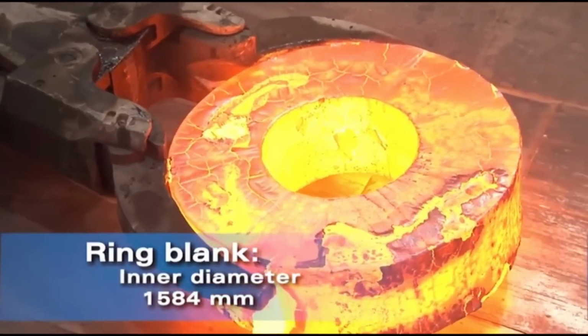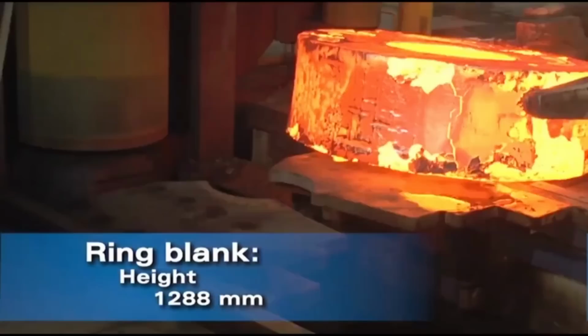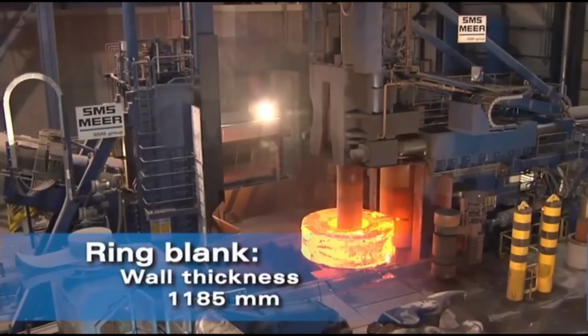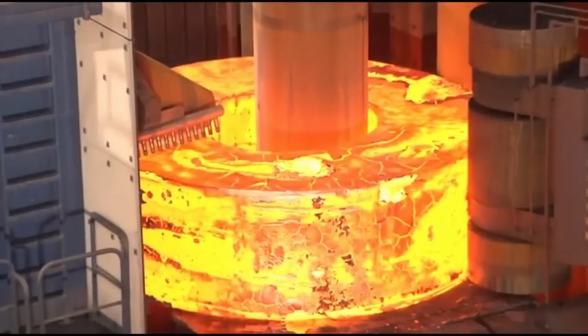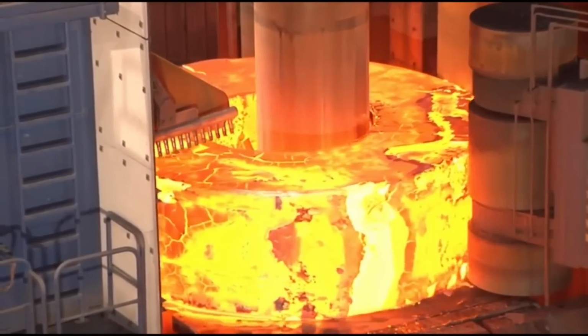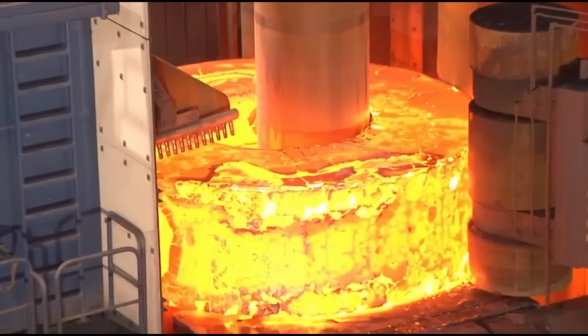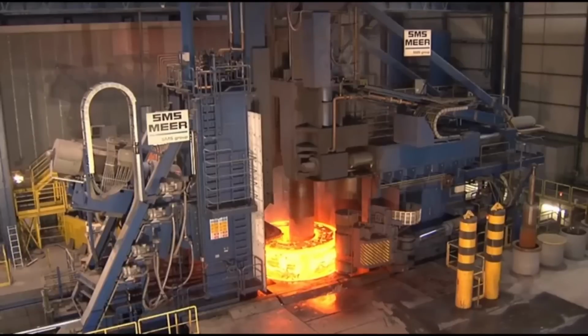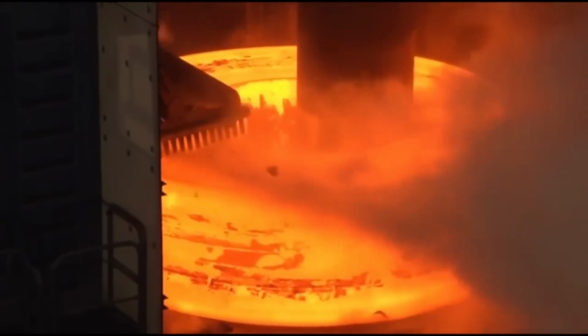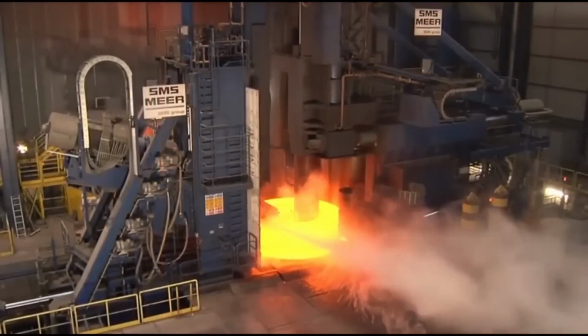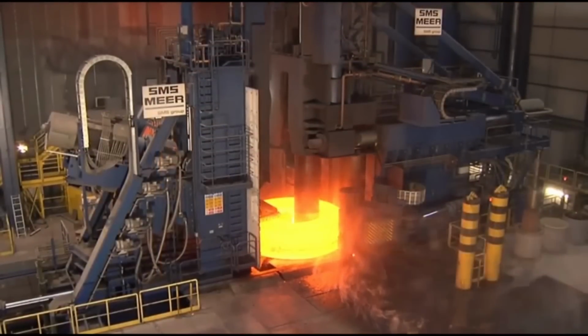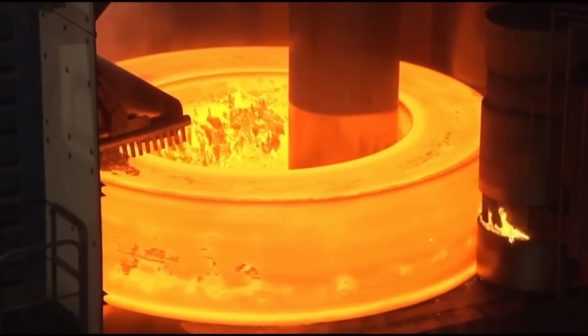Outer diameter, 3,954 millimeters. Inner diameter, 1,584 millimeters. Height, 1,288 millimeters. Wall thickness, 1,185 millimeters. A much larger ring blank with an outer diameter of 3,954 millimeters, an inner diameter of 1,584 millimeters, a height of 1,288 millimeters, and a substantial wall thickness of 1,185 millimeters is subjected to the rolling process. This larger blank requires more extensive deformation, showcasing the machine's capability to handle significant material volumes.